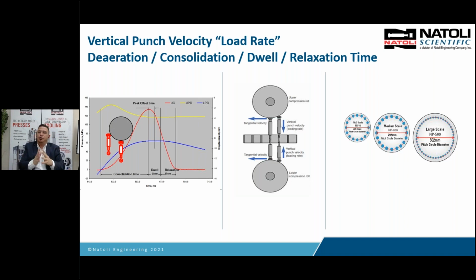And if you take a look at new machines today, you'll notice that the pre-compression roller is the same diameter as the main compression roller. Why is that? Because pre-compression purpose is to get the air out and consolidate. So the larger the roller, the more effective that pre-compression is going to be. Where if you had a small roller, it's not going to be so effective for pre-compression as a big roller. Okay, so it's not the amount of force you put on, although if you put too much force on and you create bonding, that's an issue. But the more time you have to get that air out and consolidate the particles will benefit pre-compression.